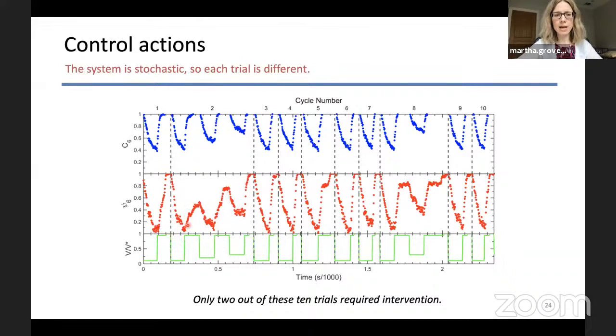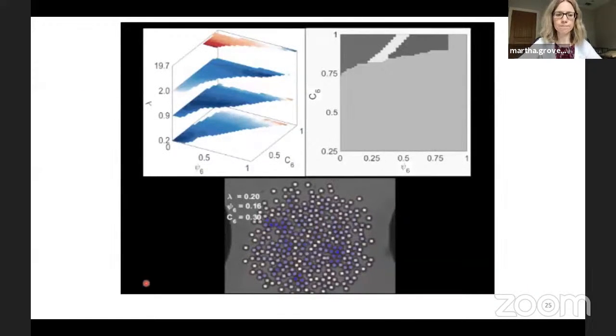But here, size 6 did not go up all the way. We have a grain boundary, so we relaxed according to the policy. We needed a couple of times to relax it, but finally it does assemble. Many of the cases did not require intervention, but some of them did. And that's really why we need control, because the system is stochastic, so each trial is different.